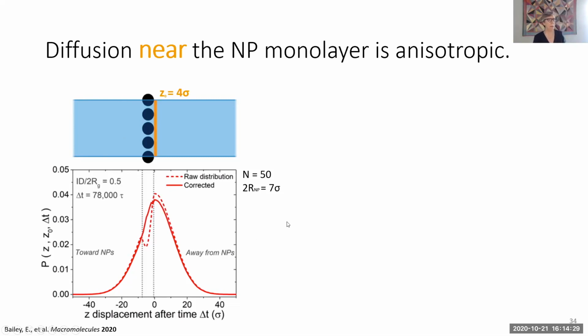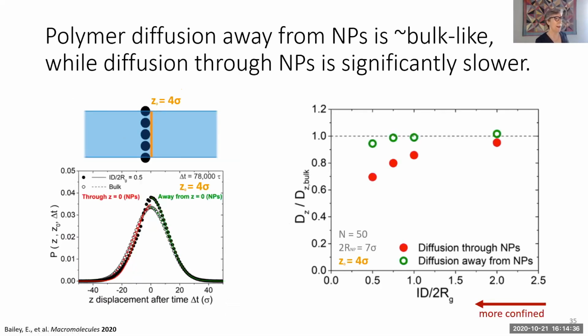And what might be hard to see from this is that there is actually anisotropy to that solid curve. It is no longer Gaussian. So here I've reproduced the data that was on the previous slide. The bulk is in the open circles, and you fit that with a nice symmetric Gaussian. And then for the monolayer, where we're right outside the particles, those are the filled circles. And you're fitting it with 2 different half Gaussians, to fit diffusing away from the particles as opposed to diffusing towards the particles. And now we have the interesting result, which is that the diffusion in the Z direction is nearly the same as the bulk when you're diffusing away from the particle, but diffusing towards the particles is slower.